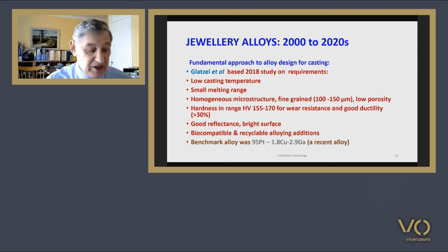A more fundamental approach to improve casting alloy design has been undertaken recently by Professor Glatzel and his co-workers at the University of Bayreuth in Germany. They looked to develop an improved casting alloy of 950 fineness with the following requirements: a low casting temperature, a small melting range, a microstructure that is homogeneous, fine-grained in the range of 100 to 150 microns, and with low